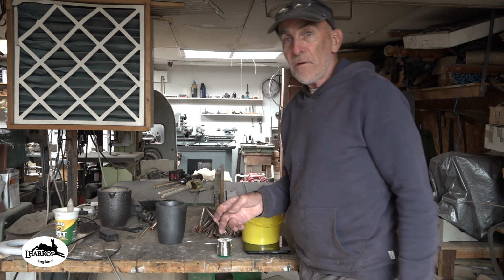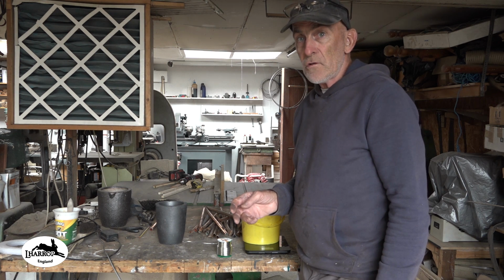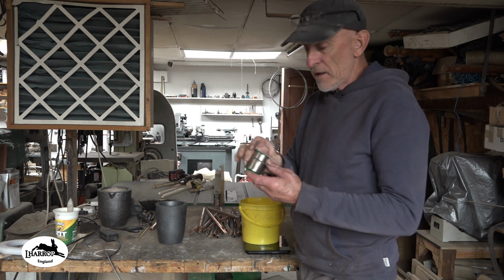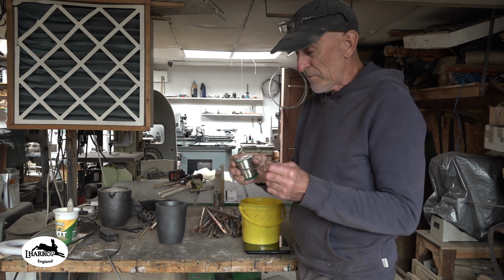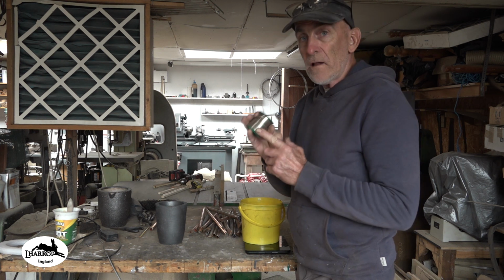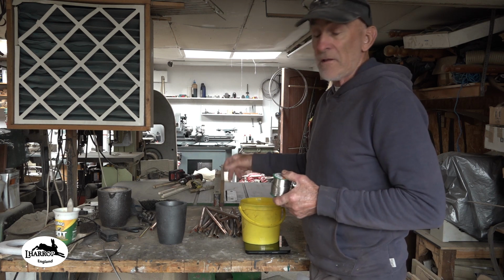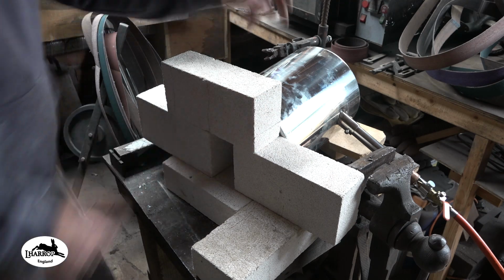And today I'm going to melt some copper and solder to make a tin bronze. So lead-free solder is 99 point something % tin. I think there's a bit of zinc in it or something like that. So I'm going to be using 12% of the solder and 88% of the copper.